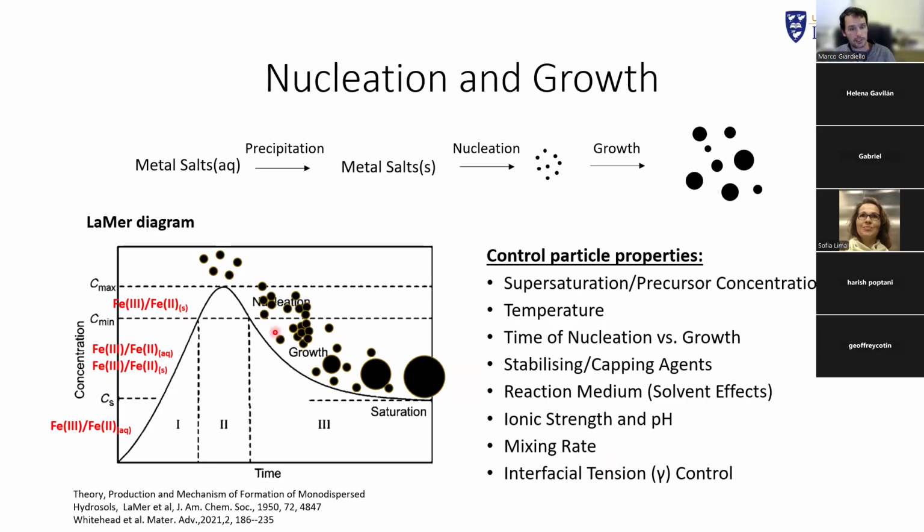Mixing would have an effect, because if you mix really badly, you wouldn't have a uniform diffusion, or if you mix really well, you have a wide, rapid diffusion. And then things like interfacial tension and the surfactants that you have in there, because you're creating a new surface. So obviously, if you're creating a particle, and you've started in liquid, you are creating a new interface, and the whole colloidal system dynamics that are associated with interfacial tensions start to kick in as well.